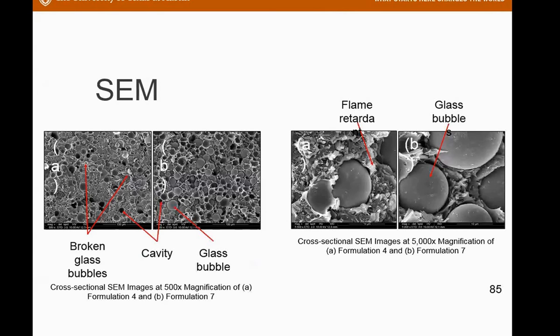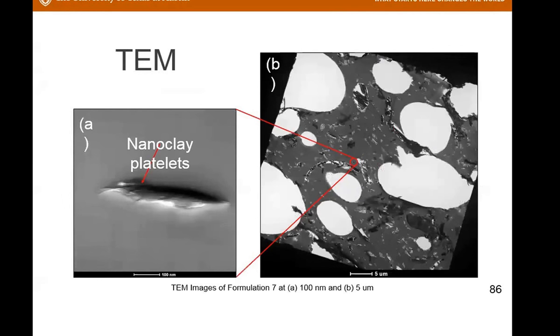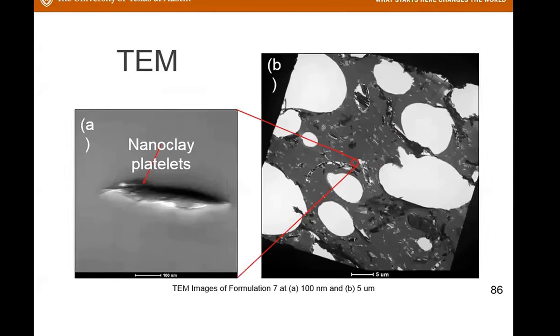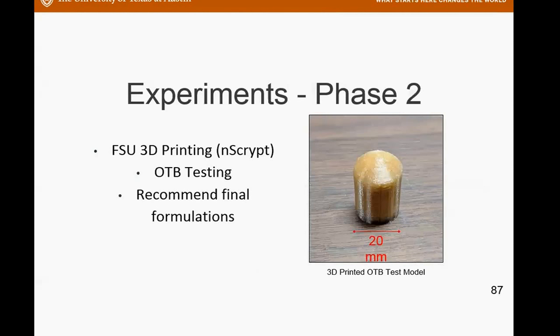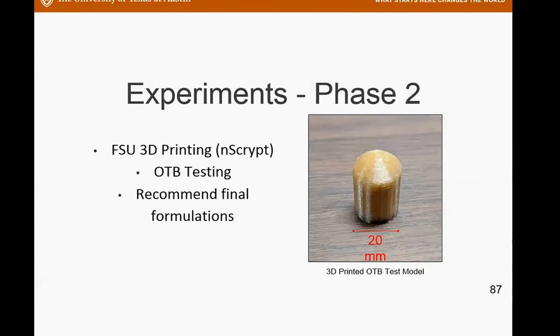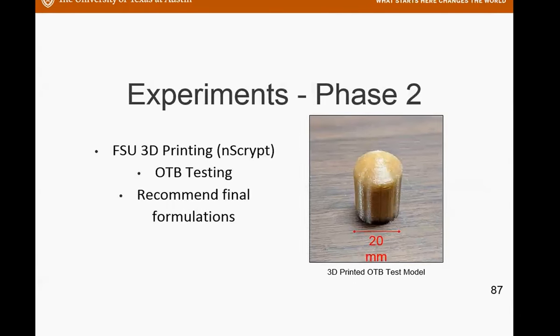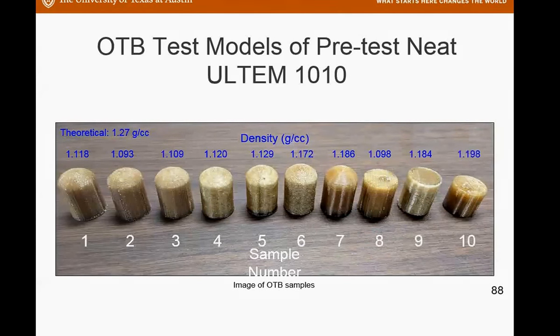Okay, so we verify that, and we look at the bubbles, and the flame retardant, and we also look at TEM and look at the clay dispersion. Basically, this clay is not functionalized, and that's why this is what you call an intercalated state in your PEI. Okay, so we print, we send this to FSU, and using nScrypt we actually print a very decent part. This is a neat system, and this is what we call a test model. This one is 20 millimeters. Okay, and we put it in the material, and we print all these things.